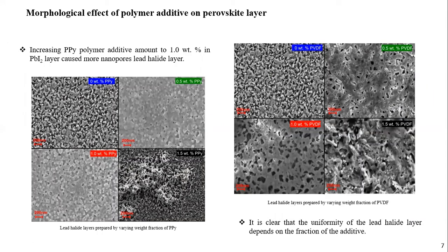Perovskite layer growth and morphology strongly depend on the lead iodide layer. Normally, a compact lead iodide layer without pores is not desirable because it can prevent facile reaction with methylammonium iodide. Getting a smooth lead iodide layer with small nanopores helps effective methylammonium iodide diffusion and expansion, which is really required to eliminate the residual lead iodide and to obtain much smoother perovskite layer.